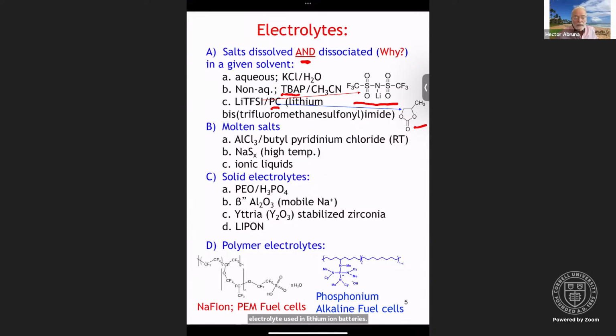You can have polymer electrolytes. The most common one, Nafion. Notice how I spell Nafion, because the name derives from sodium fluorinated ionomer. This is the key element in PEM, which stands for polymer electrolyte membrane fuel cells. You can think of Nafion as essentially sulfonated Teflon. So here you have what looks like Teflon, sulfonated side chains. This makes this environment very acidic. It forms inverse micelles, so you have channels where you have the ionized sulfonic acid groups that can transport protons. And so that's why, for proton exchange membrane fuel cells, this is the ionomer and membrane material that enables you to transport counterbalancing charges.